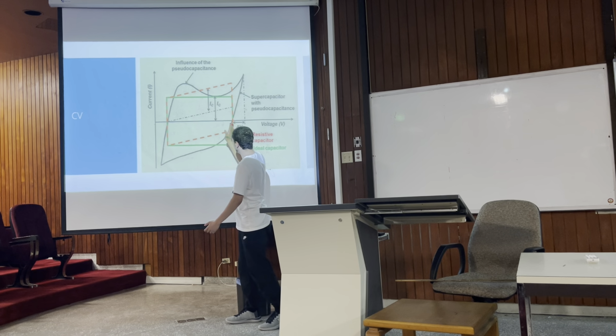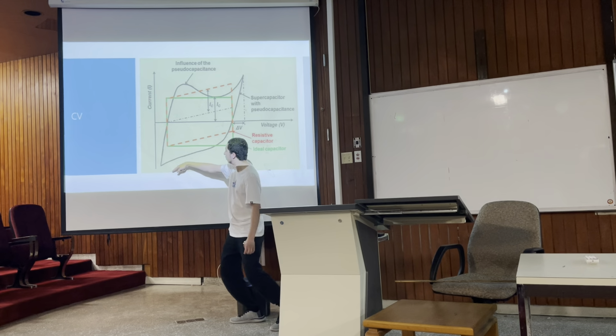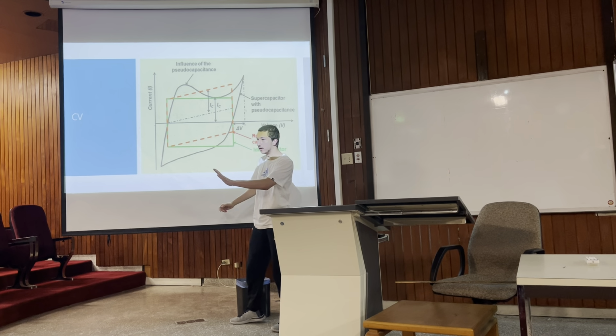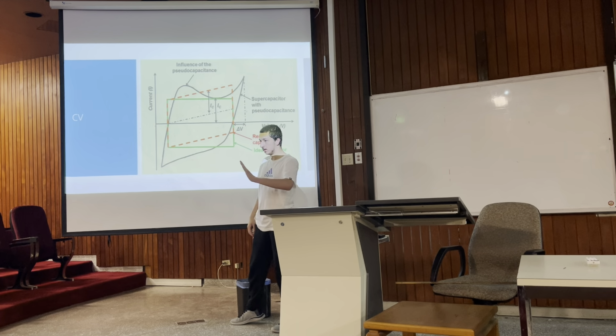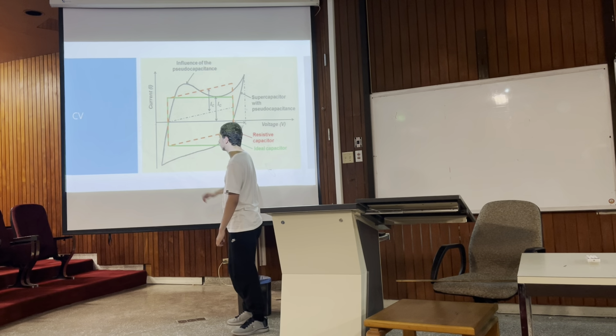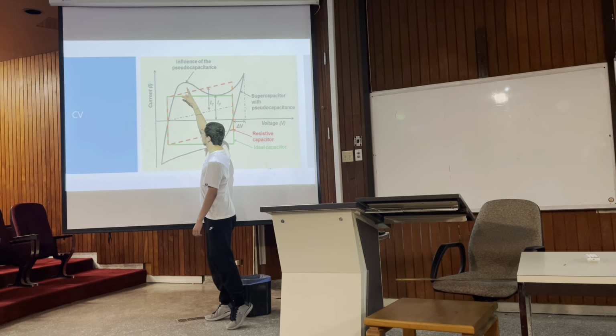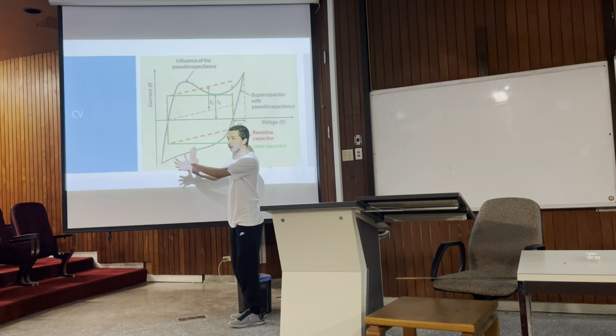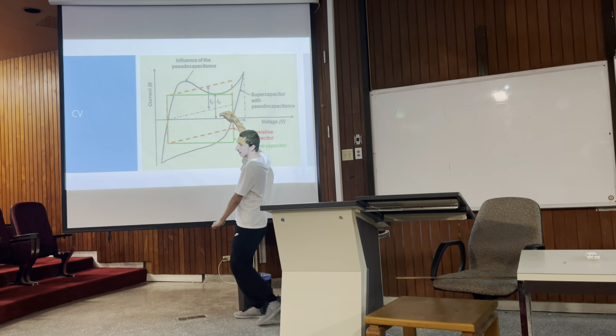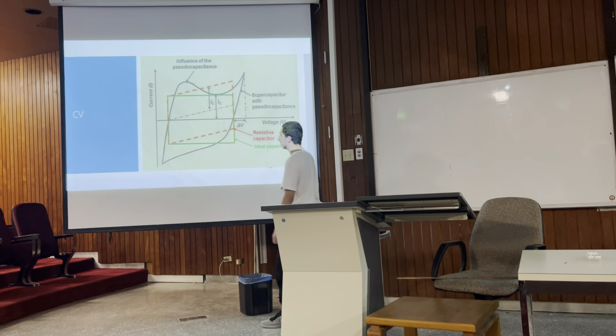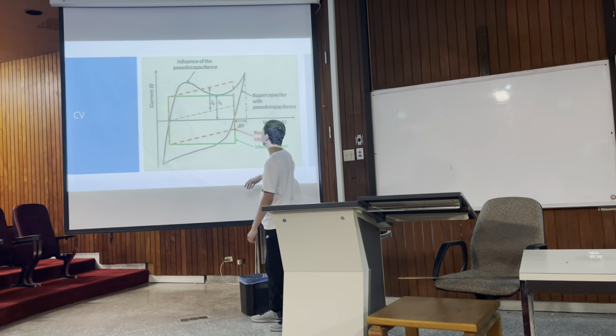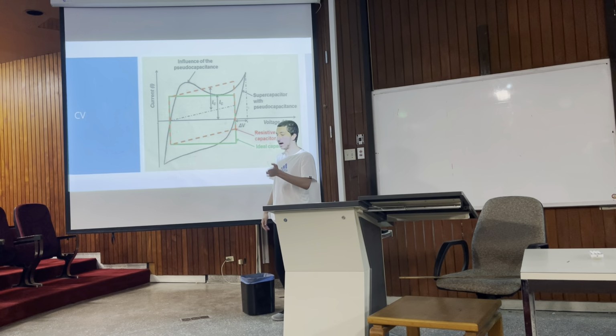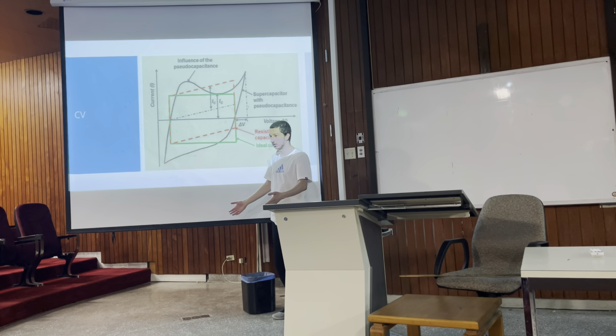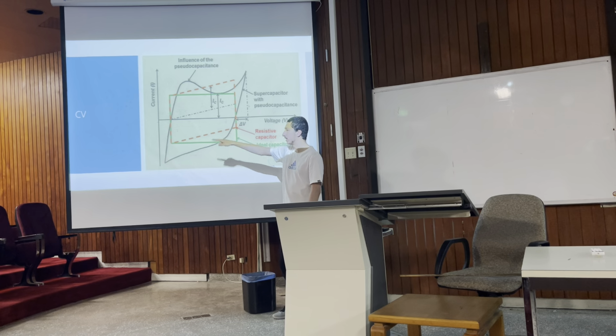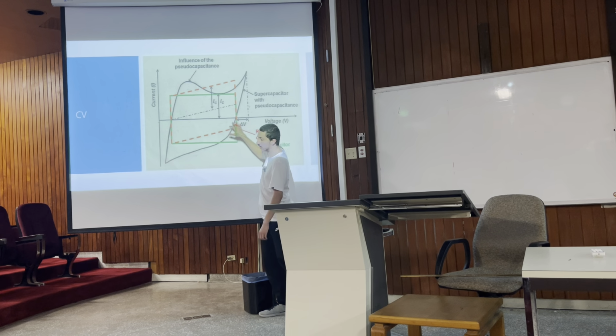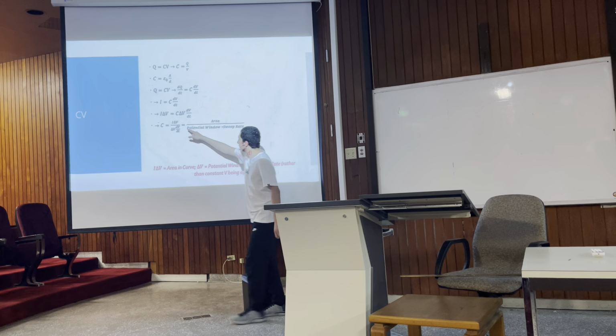When you charge it, you go from usually 0 volts. First there's a spike when there's an initial push of ions, or electrostatic push, and then you get to a peak, and then there's almost like crowding in the middle. So there's a decrease in the current that you can attain. Then there's an initial push at the end, where after the saturation you come close to the breaking down of your capacitance. A similar effect happens when you discharge. So this is the area, I delta V, that's present here.